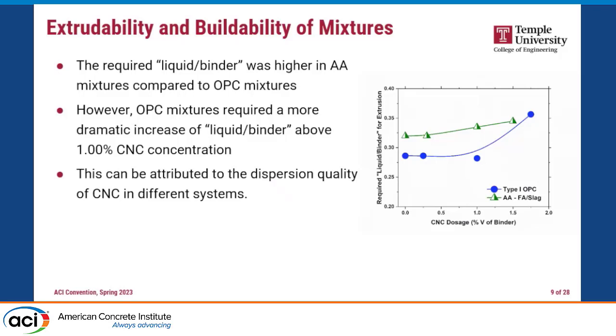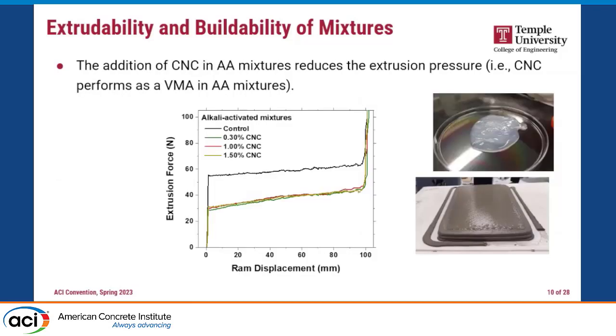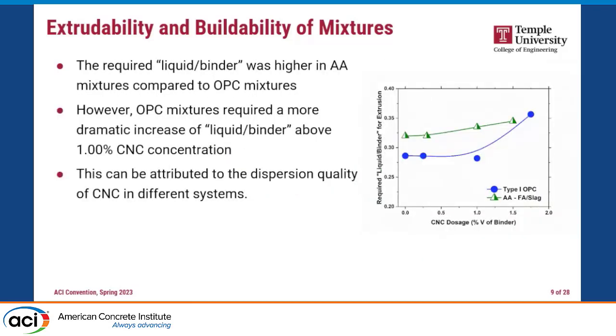Regarding the fresh properties, this is what I'm showing at the right side here. The x-axis is the CNC dosage, the y-axis is the required liquid to solid ratio to be printable. As you can see, for alkali activated system we need more liquid to binder ratio to be printable, but for OPC lower. Something we notice is that after 1% CNC use, we see a higher exponential increase in the case of the OPC, and that's the critical point to reach agglomeration and aggregation of the CNC in the OPC system.